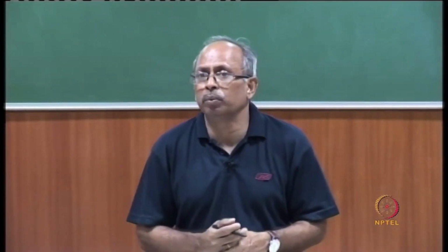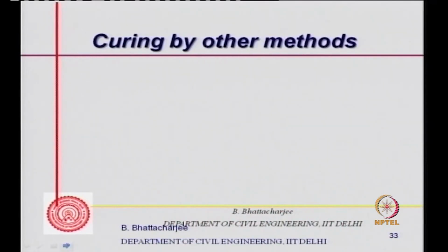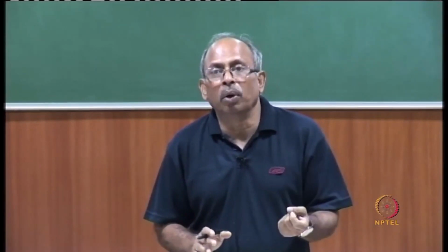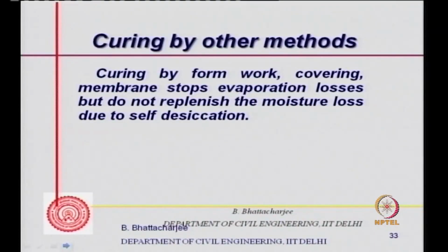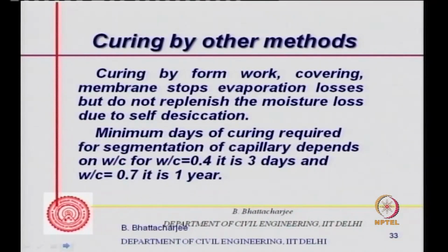So cylinder strength, okay, basically what we want to see is the qualitative, because quantitative values don't make much sense, as they will vary from concrete to concrete. So ponding is a good thing when you have the facility and the possibility of doing it. For example, you can do ponding on slabs or horizontal members, particularly large horizontal members, but you can't do it on columns. Curing by formwork covering or membrane, of course, stops evaporation, which I said, but does not replenish the moisture loss due to self-desiccation. That's a problem.